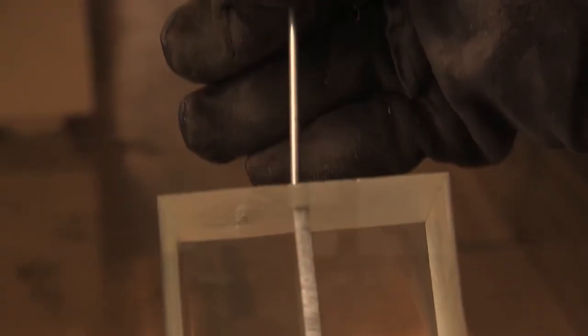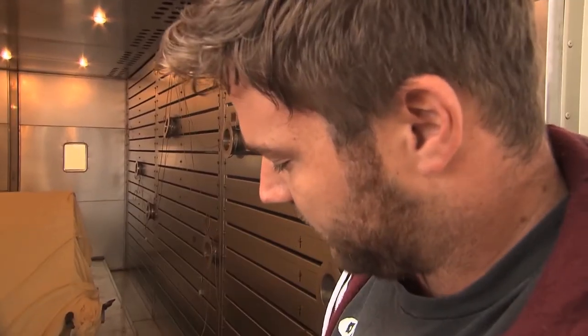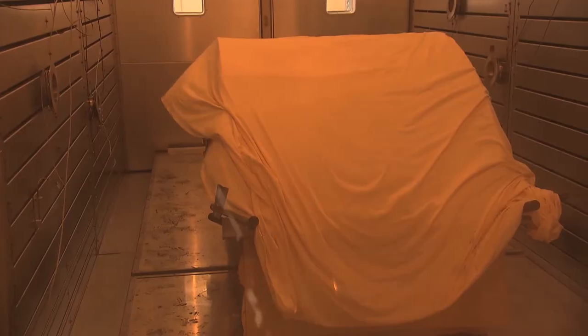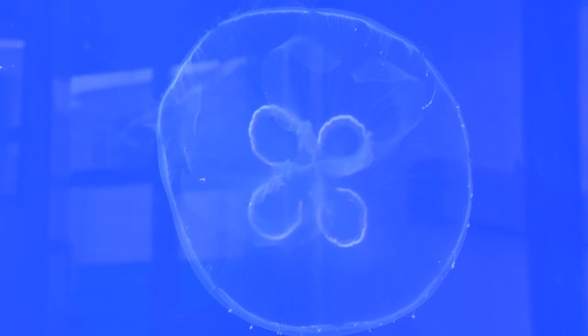At the moment it's about 320 degrees Fahrenheit in the oven. We measure the temperature with a sensor and a sample block which has a core drilling. In this way we get continual feedback as to how warm it really is inside the block. Afterwards, it has to cool down just as slowly so that no stresses occur. That means tomorrow morning it'll be about 105 to 120 degrees Fahrenheit, then we can turn off the oven and let the acrylite cool down slowly over the weekend.